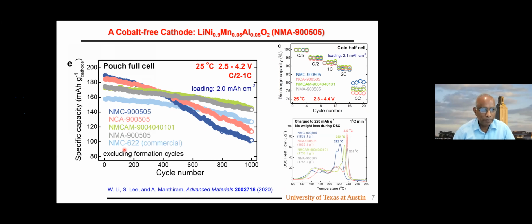I'm comparing 5 materials here. 4 of them have 90% nickel and 1 of them has 60% nickel for comparison. This is the material NMA, meaning 90% nickel, 5% manganese, 5% aluminum. The composition is written on the title. And the performance is here. This is a pouch cell, 1000